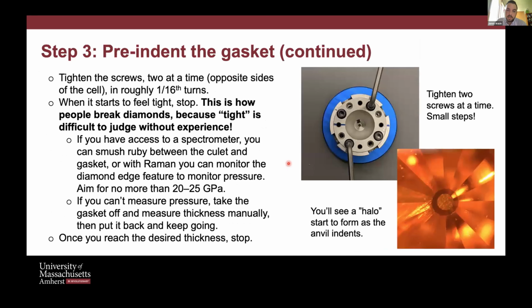The second most dangerous part is actually tightening itself. This is where we start to now tighten these screws. As we tighten the screws, we're bringing the cell together, applying a force to the anvils that's then going to push the diamond tips into the rhenium and push that away. That rhenium will start to flow away from the culettes. We're trying to get to the point where we've still got some plasticity left in the gasket for it to collapse during the experiment, but we've got rid of most of that softness. So we're trying to find that sweet spot.